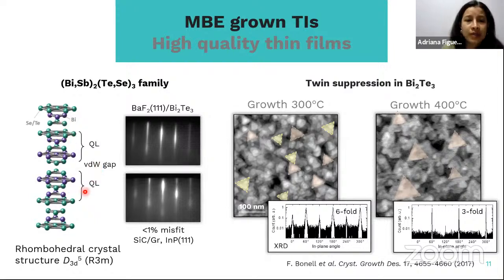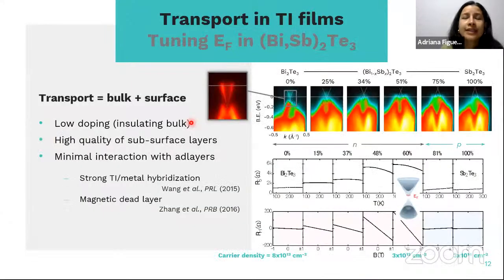And we have optimized the growth of these TIs on barium fluoride, which is the substrate that we use in this case. It has been established what the conditions are to suppress the appearance of twins in the system, so that we end up with a smooth surface on top of these TIs. And why is this relevant? This is relevant for studying and taking advantage of the electronic transport properties in these TI systems, in these films.